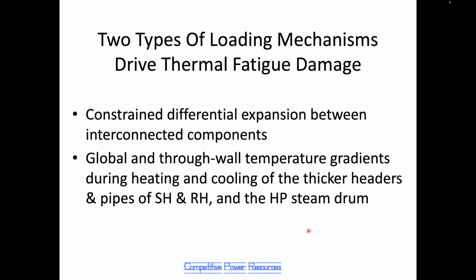The two types of loading mechanisms that drive thermal fatigue most commonly are constrained differential expansion between interconnected components, which means, let's say you have two tubes connected to one upper and one lower header. One of those tubes operates at a higher or lower temperature than its neighbor. The tube that's at the different temperature will try to expand or contract compared to its neighbor, and that will create large system loads, generally at the tube to header weld.